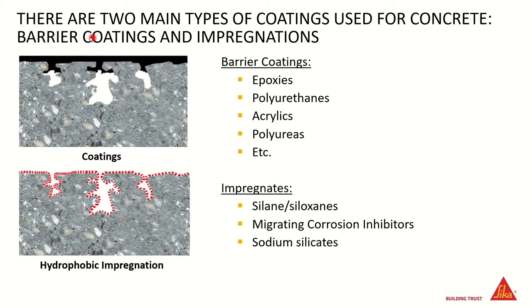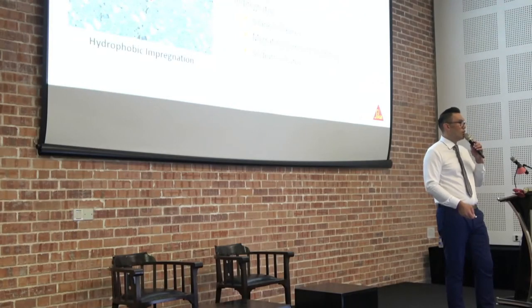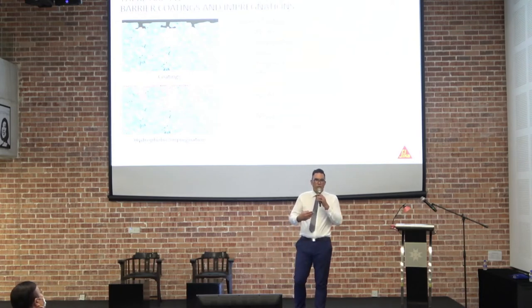The barrier coating is solid and doesn't allow anything to get in, but equally it doesn't allow anything to get out. So if you have moisture inside your concrete that wants to get out, this is where you end up with bubbles. You may have seen on some buildings where they're coated that you have big blisters. It's not a failure of the coating. It's just part of the natural process of the water escaping from the concrete, and that pressure is enough to even overcome the bond of epoxy to concrete. So we end up with osmotic blistering, and we can't stop that process happening without addressing it to begin with.